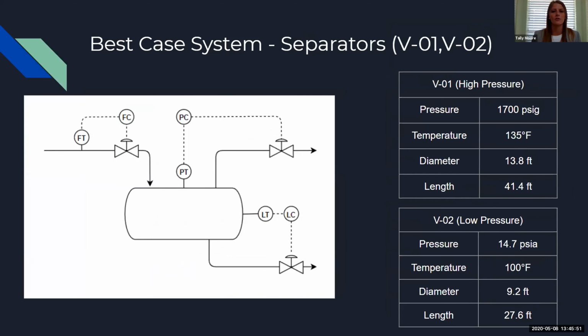And then we've got both our separators, our high and low pressure separator. The high pressure separator was at 1700 PSIG and 135 degrees Fahrenheit. Its diameter was 13.8 feet and its length was 41.4 feet. And the low pressure separator was at 14.7 PSIA and 100 degrees Fahrenheit with a length of 27.6 feet and a diameter of 9.2 feet. And we'll go into how we got the specs of each of these based on optimizations later on.